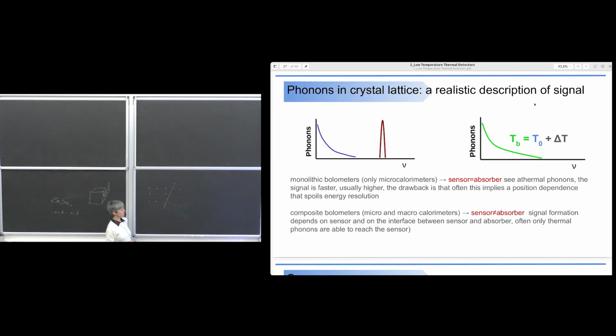However, this is the case in which your sensor is identified with the absorber. The problem is that often in the readout of these thermal phonons, you see a position dependence, and therefore you lose in energy resolution, because you have two variables in your signal. One is the position where the energy is deposited, and the other is the amount of the signal that you produce.